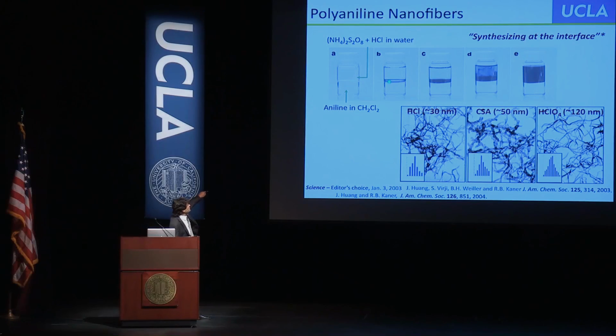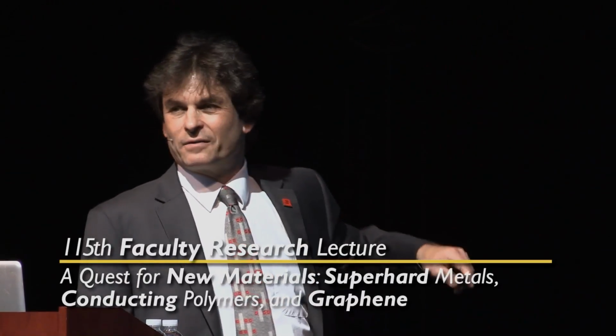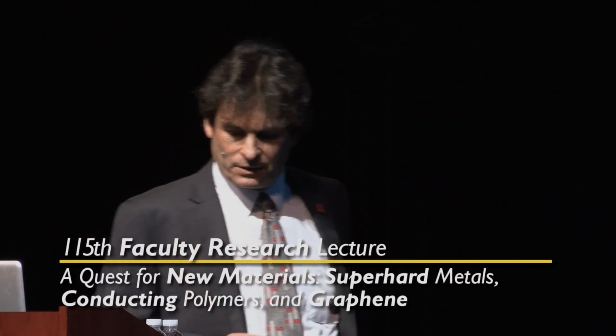Why can you see it? Because it's conjugated, and therefore it absorbs visible light. So as soon as you see it, it's forming. Now, this is a minute, 2 minutes, and 3 minutes. You'll notice that as it forms, it goes into the water phase. And that's because it forms in the doped salt form. And so it disperses in water. And we particularly chose a more dense organic phase so that gravity has nothing to do with it.